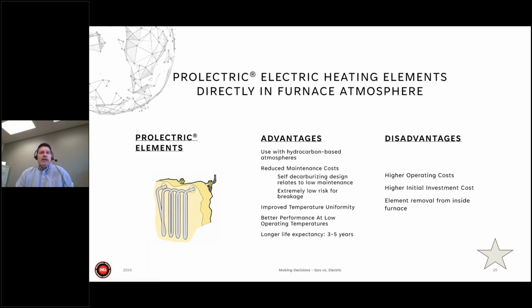This electric heating element is also good for hydrocarbon atmospheres, such as RX gas for carburizing, endothermic gas. And as shown in the photo, the element is actually a bent tube that has an airstream going through the center of it. So it's 330 alloy, so it's good for these atmospheres. The airflow through the center actually helps self-decarburize, pulls the carbon out of the tube, so it extends the life. And it's a very robust system.